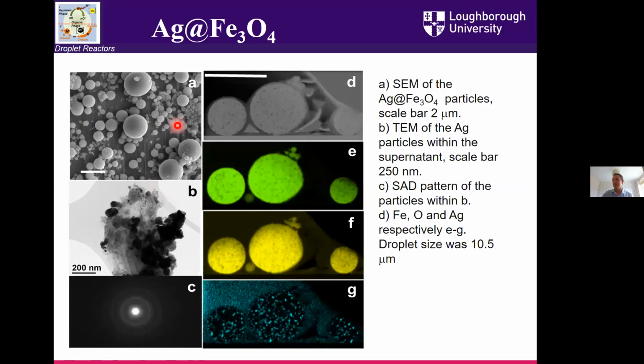When we cut these open, going back to my simplistic schematic, silver shell on the outside, iron oxide in the middle, you cut them open and you do the elemental analysis, and what you hope to observe is some sort of shell on the outside which is metallic. And what you're seeing in the images here is the SEM. And then as we go through the elements here, I've got iron and oxygen. That's throughout and continuous, so you would expect that.